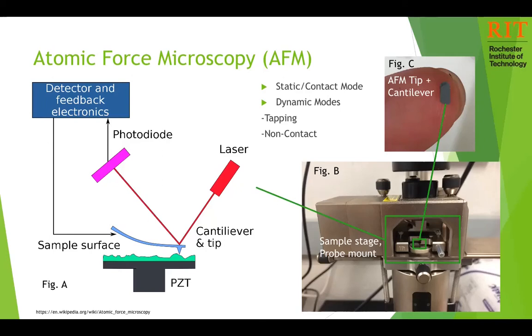A piezoelectric ceramic scanner controls the position of the probe relative to the sample surface. As the tip moves over the surface, the probe will then be deflected according to the surface topography, which is tracked by a laser and a position-sensitive photodetector, as shown in Figure A. This information is used to construct a high-resolution 3D image of the surface topography.